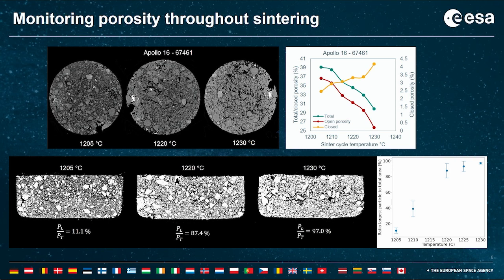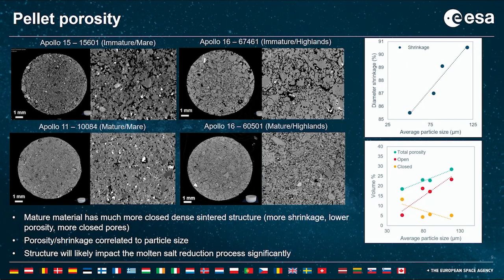And this is a bit more of a comparable way to compare materials of very different porosities. So we can apply that to the next data set as well, and then look at the materials compared to each other in terms of the final pellet porosity and structure. You can see here that the top two examples, the two immature ones that have the higher average particle size, have a quite different structure, much more open structure and much larger pores.